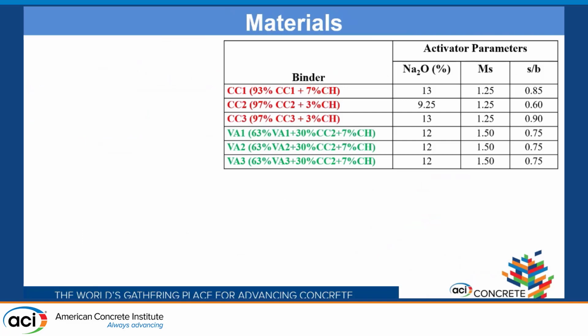So for this study, we have used 3 different types of calcined clays and 3 volcanic ashes sourced from different parts of the US with varying oxide compositions as shown in this table. Looking at the particle size, VA2 is the finest one and CC2 is the coarsest one. These 6 aluminosilicate powders are then activated using a hybrid solution of sodium silicate and sodium hydroxide. However, they are further blended with calcium hydroxide in the case of CCs, and in VAs they are blended with CC2 and calcium hydroxide to enhance their engineering performance.